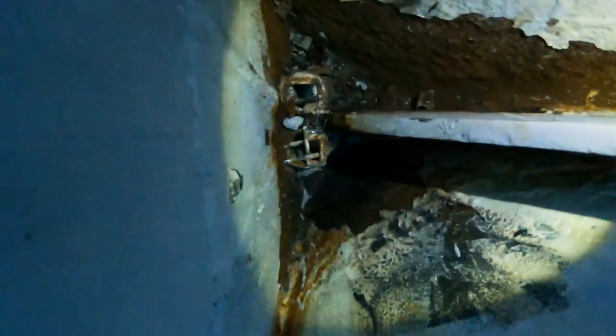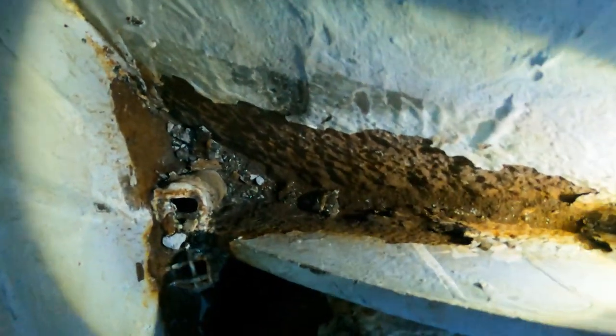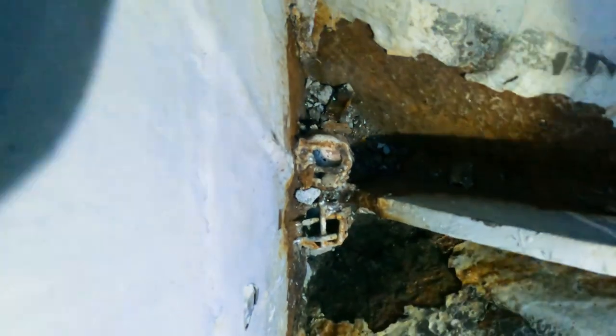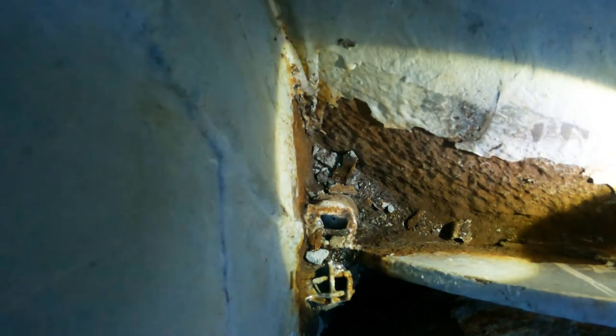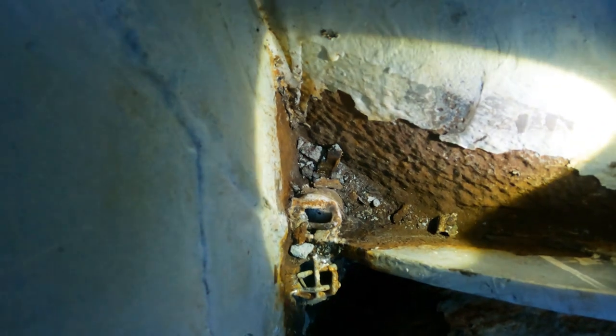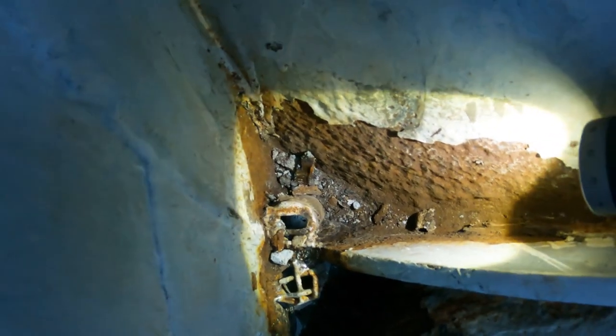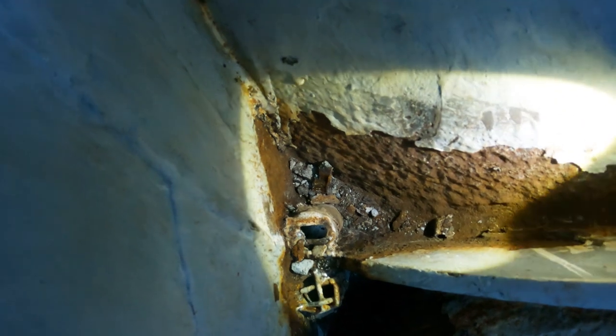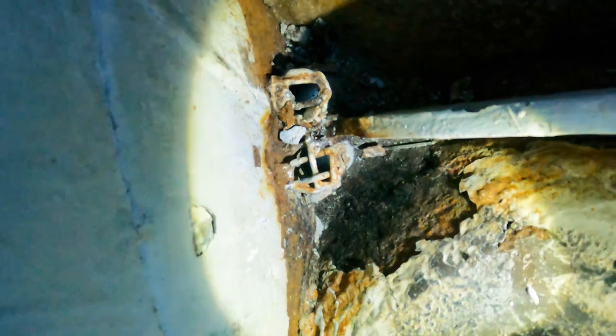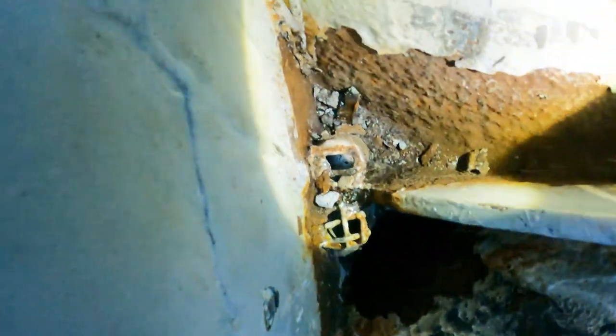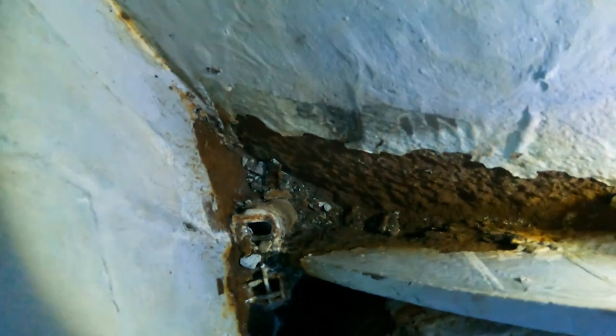So I've got most of it out. But she's had a bit of metal loss. It's not going to alter the integrity of the boat. But I may do an ultrasonic thickness test on this part of the boat just to make sure. But as you can see, a little bit to get down in the bottom. But that was a really bad move by whoever did that. But I'm glad I got all that concrete out.